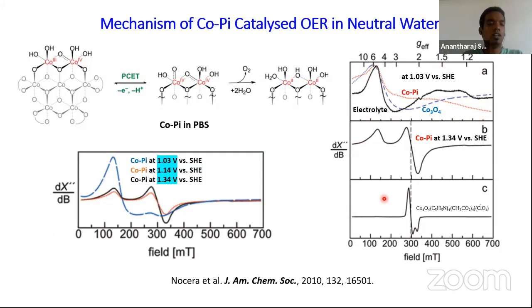Let's see one by one. In the case of cobalt catalyzed proton coupled electron transfer reaction for water oxidation, the group of Nocera et al. have done many works on this particular material, and they initially proposed there was the formation of cobalt 4+, because cobalt 4+ is not a very common oxidation state of cobalt that we encounter in our lab every day, doing everyday chemistry. It is very rare to form cobalt 4 plus species in our experiment.